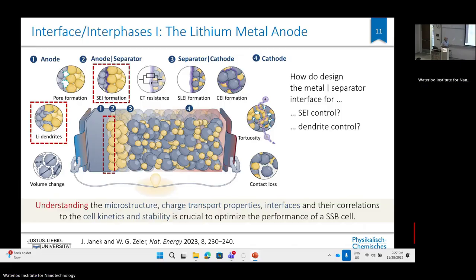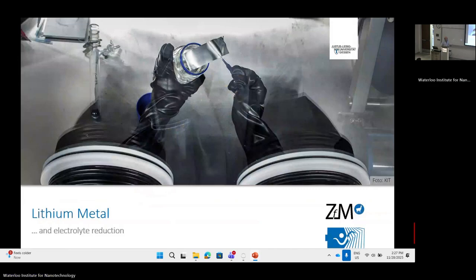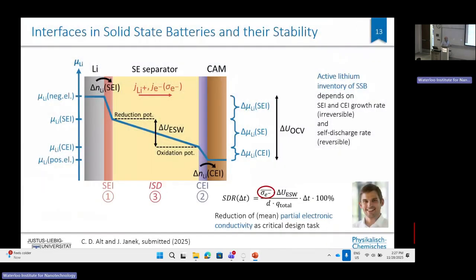Okay, so let's look first, as I said, into interfaces. Let's look at the negative electrode interface, and let's believe we can operate with lithium metal, and see whether the electrolytes are stable. And this is an important subject that, in fact, in any kind of solid state battery, the same cartoon could in principle be designed for a liquid-based cell. The negative electrode has a very high chemical potential of lithium. If you work with lithium metal, it is the highest chemical potential of lithium you can take, the standard potential of lithium. So this is chemical potential, not electric potential at the ends of your cell. The electric potential would exactly be the other way around. So there is a negative sign between the chemical potential and the electric potential. So let's think in chemical potential terms.